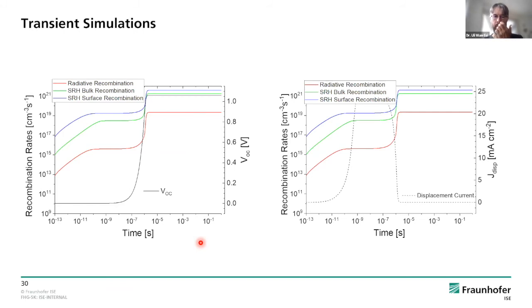For example, the open circuit voltage. The open circuit voltage here is the black curve. You can see, I mean, this is the logarithmic time scale, so nothing happens for quite some time. And then we have a rather steep increase of the open circuit voltage. Nothing too special, I would say. But it's interesting when you then look at what happens, especially here and before the open circuit voltage really begins to rise, because the time scale where it really rises is rather short.